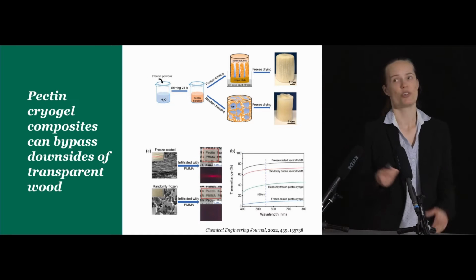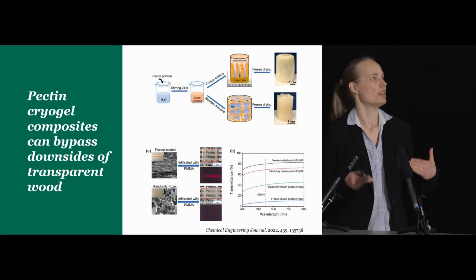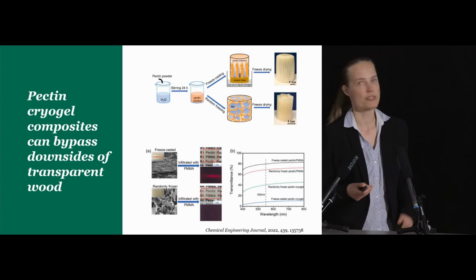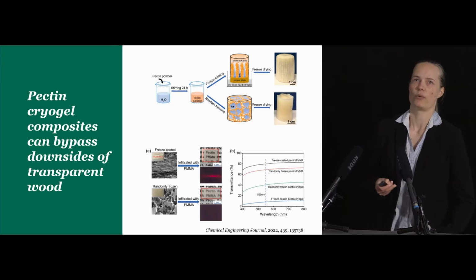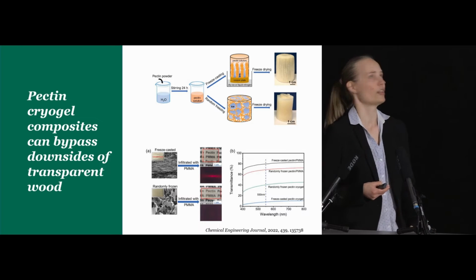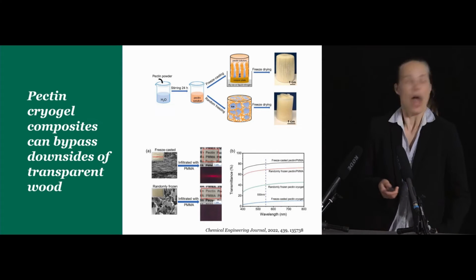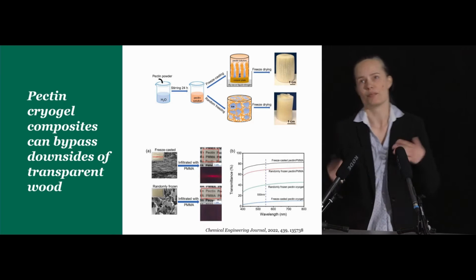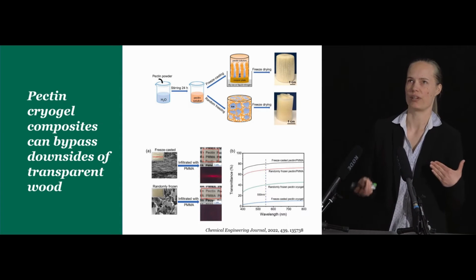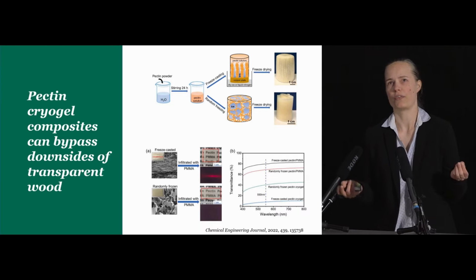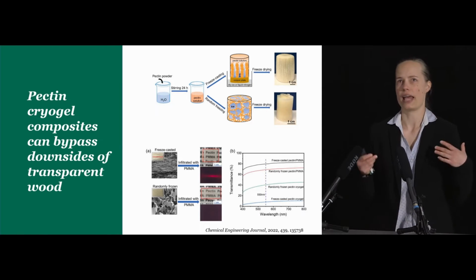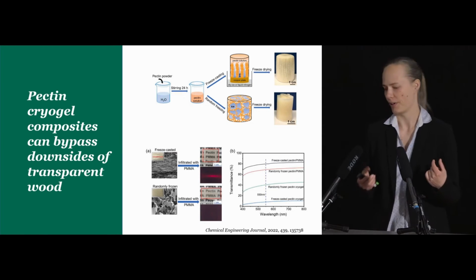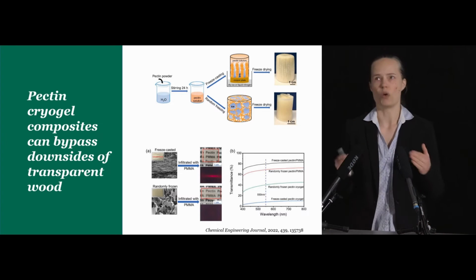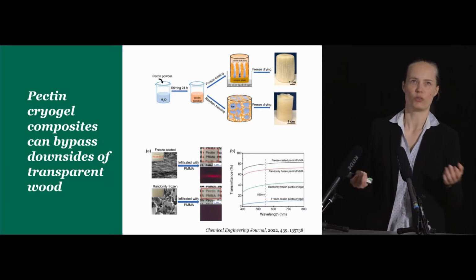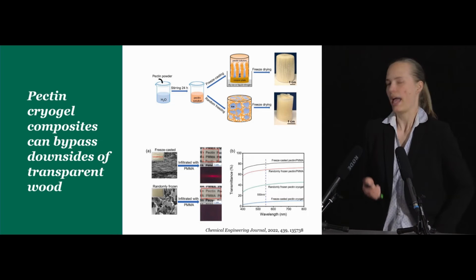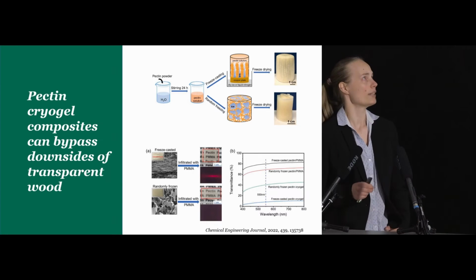Then I want to introduce a concept again for diffusively transmittant films, which is now a bit different, and we've been developing it in my lab together with postdoc Fang Xin Zhou. Here, we got the inspiration from transparent woods, where you would take a wood wafer, delignify it, and then fill in an index matching polymer. However, we wanted a simpler process, so no need to use wood as a starting material, and we started from pectin instead.